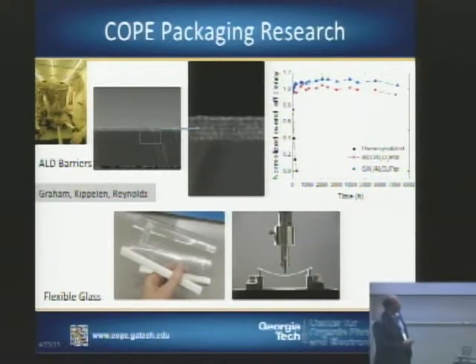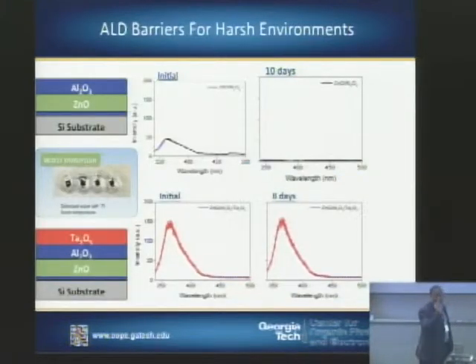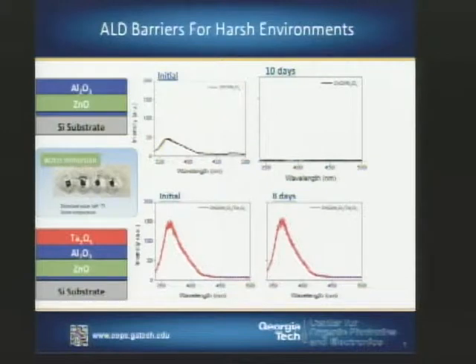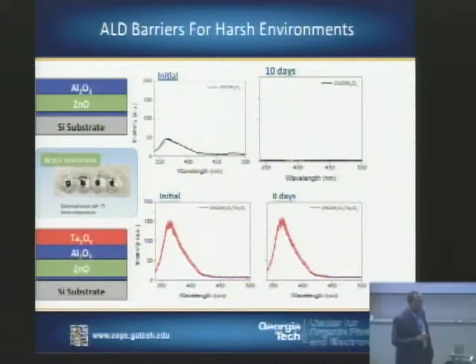So I won't talk a lot about the development of the ultra barriers and the application to OPV, but I do want to show some additional things that we've been able to do more recently. One of the things that we're starting to do is look at the application of these ultra barriers in harsh environments. In our case, we're putting these in environments that have relatively high values of humidity, or actually putting them in aqueous solutions. And this is actually a case where we're using zinc oxide as a sensor. If you put zinc oxide in water, it will basically dissolve. It will corrode.